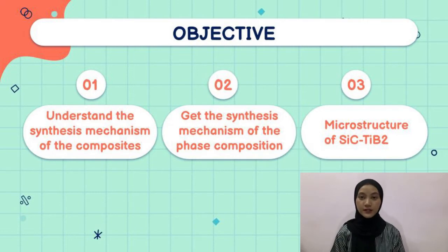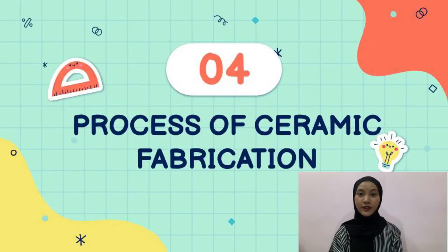were fabricated by infiltrating the aluminium silicon alloy melt into pre-sintered porous preforms with different weight ratios of B4C over TiC. It is also to get the synthesis mechanism of the phase composition and the microstructure of the SiC-TiB2. There are three different categories that have been analyzed for materials and methods mentioned in this article.